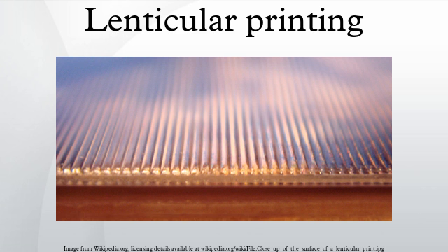Printing defects: color synchronization. One of the main difficulties in lenticular printing is color synchronization. The causes are varied. They may come from a malleable material, incorrect printing conditions and adjustments, or again a dimensional differential of the engraving of the offset plates in each color. This poor marking is shown by doubling of the visual, a lack of clarity, a streak of color or wavy colors during a change of phase by inclination of the visual.